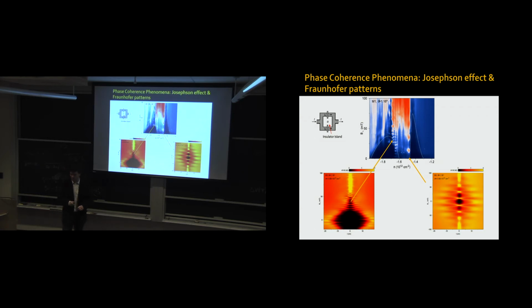If you look at the period, does it really come out to be like the moiré unit cell? So we can look at the period—it turns out it's not the moiré unit cell, and it's not the total device. So it probably means it's segregating, and some island becomes the final island when you're at that intermediate density. But we can do experiments to control this so that we make, on purpose, a given SQUID.